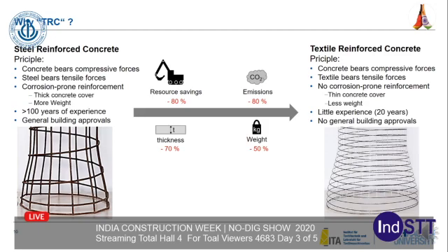However, the transition to textile reinforced concretes offers resource savings of up to 80%, leading to reduced CO2 emissions of up to 80%. Thicknesses can be reduced, depending of course on loads, by up to 70%, and the weight of building materials or precast elements can be reduced by up to 50%. In textile reinforced concrete, the principle remains the same. The concrete bears compressive forces and textile bear tensile forces. However, the reinforcement is not corrosion prone, leading to thin concrete covers, less weight. Still, the material is relatively new, with first experiences being made about 20 years ago and no general building approvals being available yet.